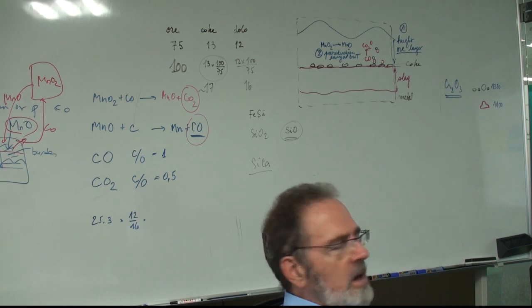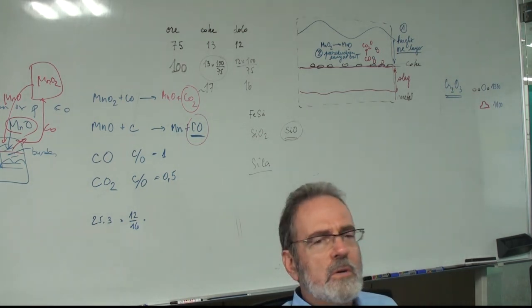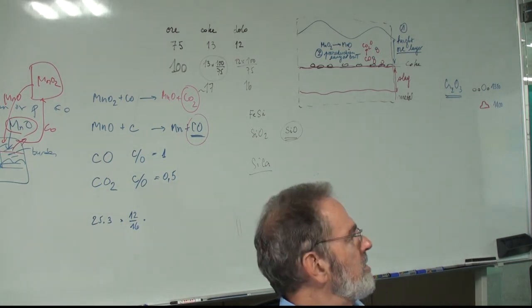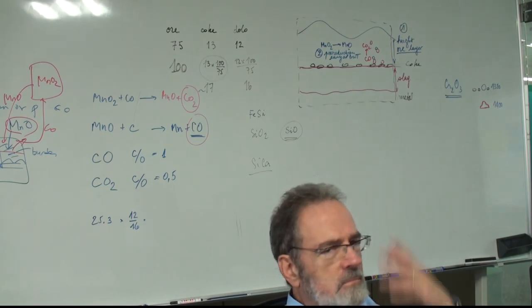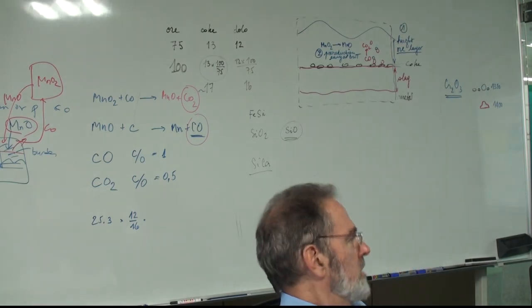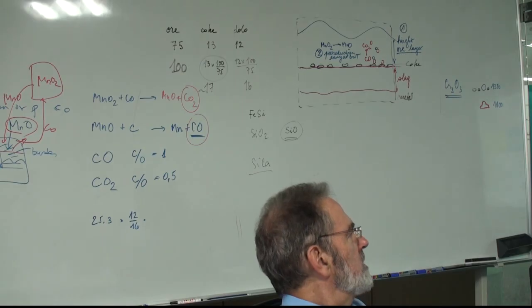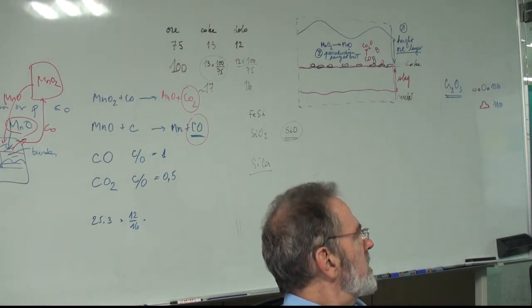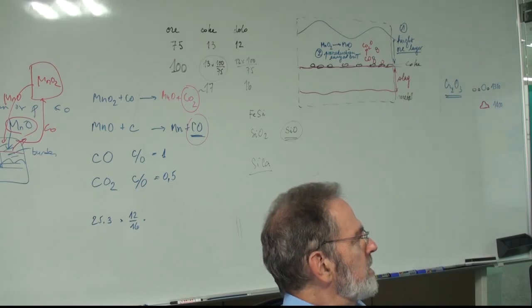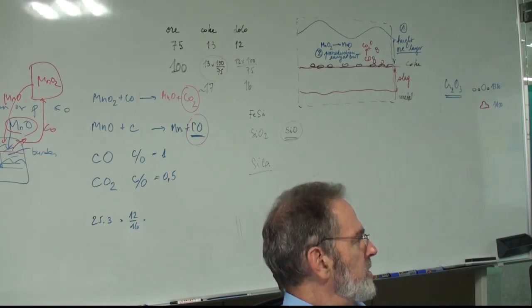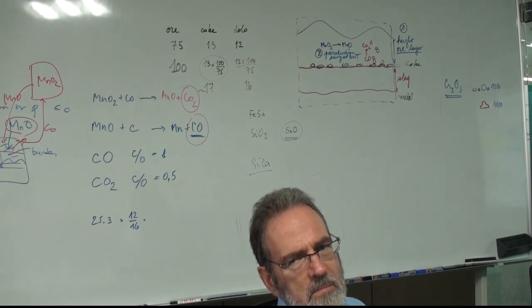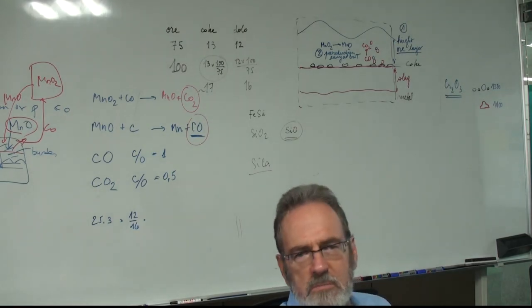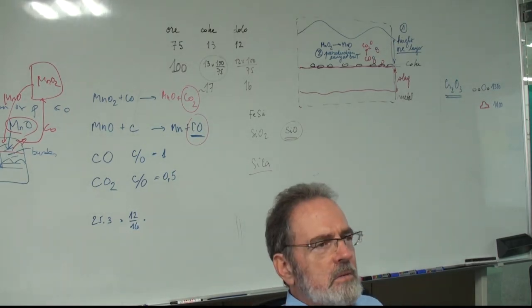And now, I had no detail on the coke quality, so I have assumed some standard data. So I have assumed 86.5% carbon and 12.3% ash. Of course, this can be variable.